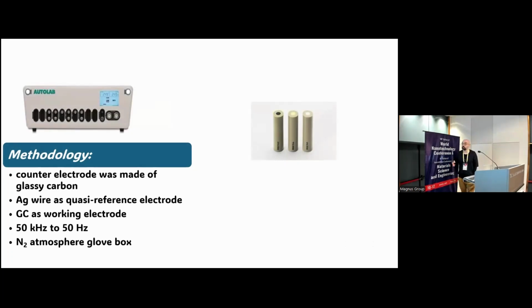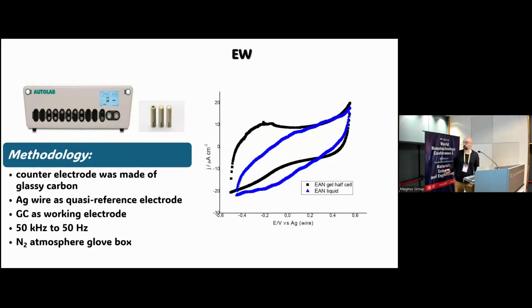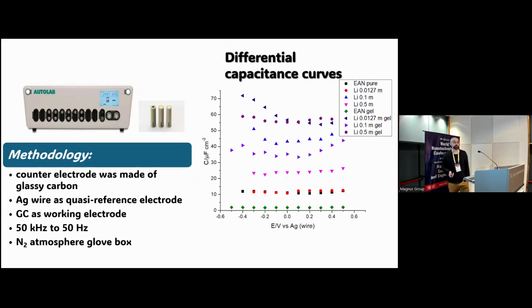To determine the electrochemical properties of the gel samples, we have to use solid electrodes. In this case, we're going to talk about the glassy carbon electrode. You can see that there is practically no difference between the ethyl ammonium liquid and the gel half cell. And studying the capacitance curves, remember the ability to store energy of our compound, you can see that the doped gel sample with the lithium presents quite big capacitance curves. We are studying these effects, and these are quite preliminary results, and it's quite tricky and interesting to analyze.